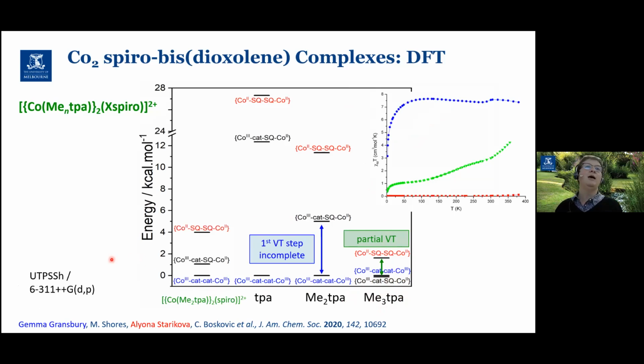And then Aliona went back and she calculated our original two-step complex, which was with the plain Spiro ligand and the dimethyl TPA, to have a look at the energies. They're exactly what they should be for a two-step transition according to what we know from spin crossover. So the cobalt-3 catechol at both halves is at the lowest energy.